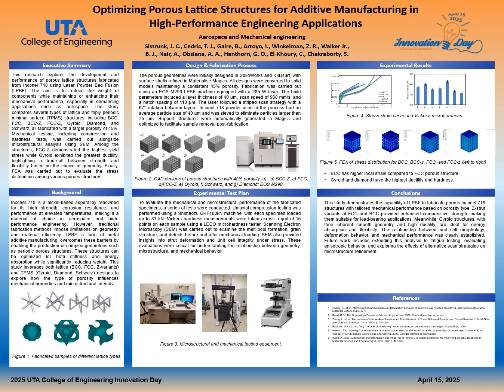We specifically used Inconel 718, a nickel-based superalloy, which is widely known for its excellent strength, corrosion resistance, and high temperature performance. In traditional manufacturing, producing complex porous structures is either extremely difficult or outright impossible. But additive manufacturing and laser powder bed fusion, or LPBF in particular, has opened up new possibilities. With LPBF, we can fabricate intricate 3D lattice structures by melting layers of powder using a high-powered laser, giving us full control over the internal architecture of the component.